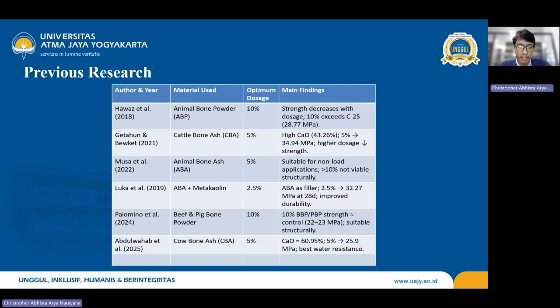The sixth is Abdul Wahab et al. in 2025, in which they used cow bone ash at a 5% substitution level. They found that the bone ash has a comparable CaO content to limestone, and 5% substitution can achieve 25.9 MPa as the highest compressive strength, and it has the best water resistance.